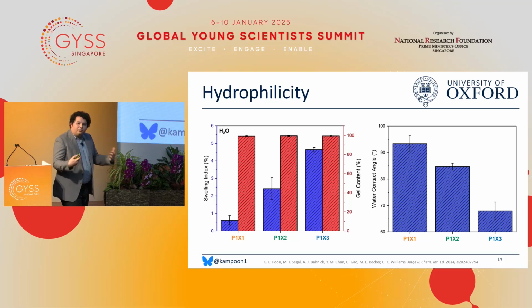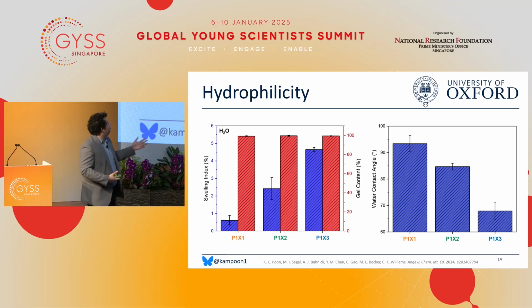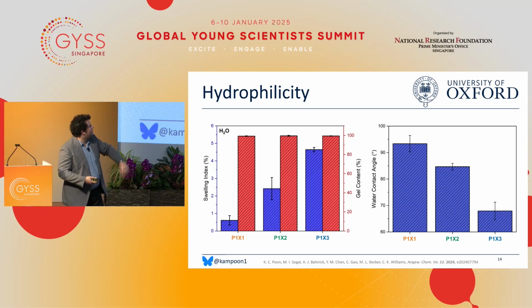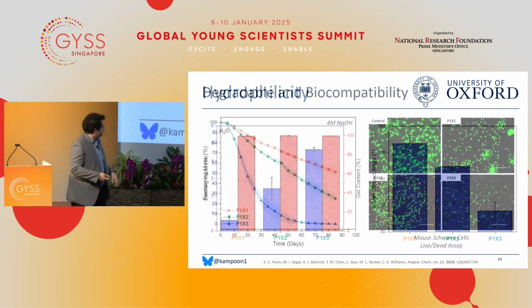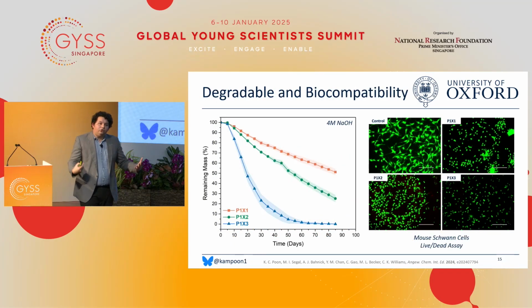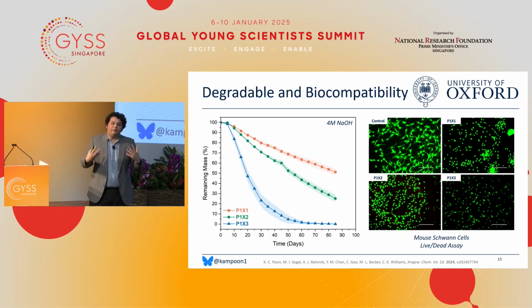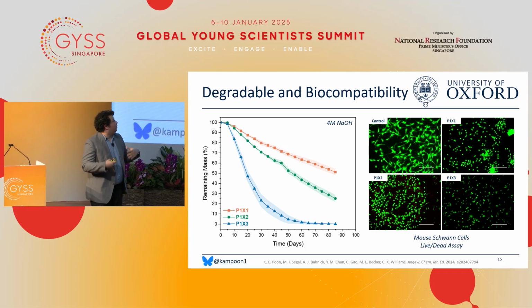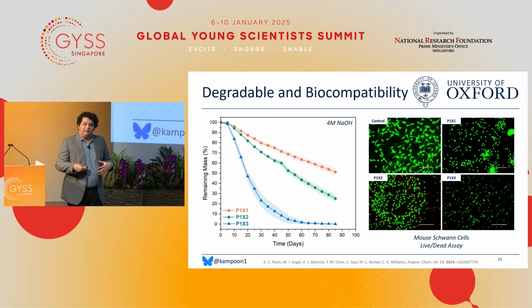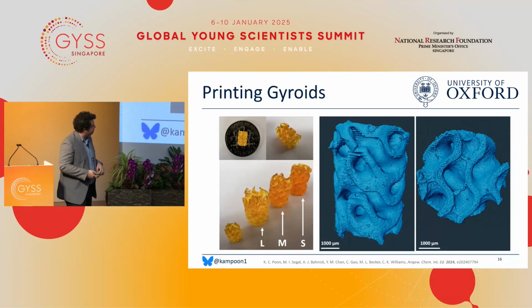We do observe the expected increase in hydrophilicity, and we can look at this through water swelling experiments as well as water contact angle experiments. And as a result, we can tune the degradation of these materials. So the higher the hydrophilicity, the faster the rate of degradation, which could open up really exciting opportunities in biomedical applications. So we had a look at some cytotoxicity experiments and saw no initial cytotoxic response for these.